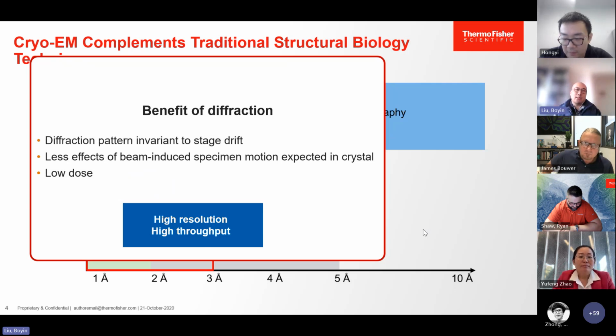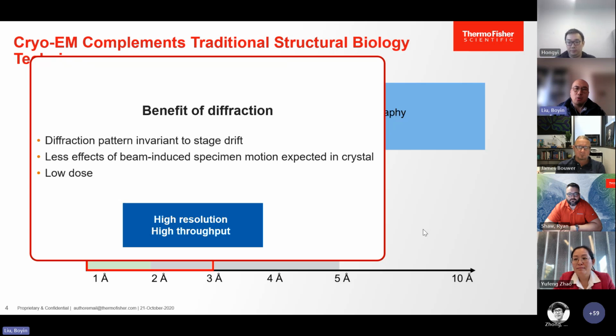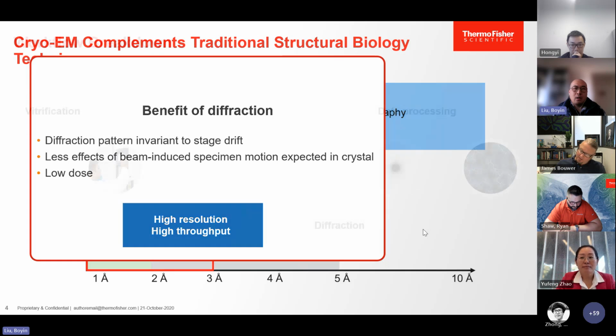The diffraction pattern is invariant to stage drift as well as beam-induced drift. In cryo-EM, instead, you have to worry about sample motion and beam-induced motion, and that the motion falls within the threshold of motion correction. And for this method, you can also do low dose diffraction. You get high resolution and high throughput data.